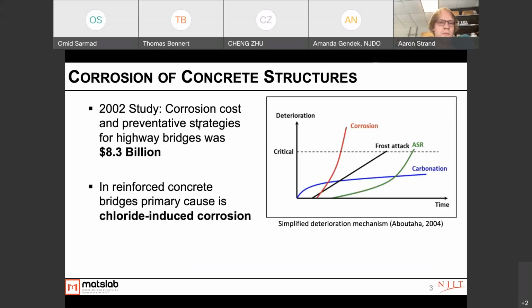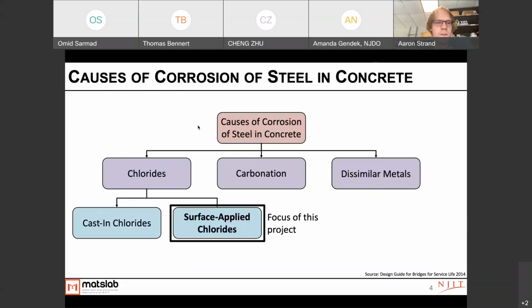So why are we concerned about corrosion? In a 2002 study, it is an $8.3 billion problem for just highway bridges. In reinforced concrete bridges, the primary cause of deterioration that we see is chloride-induced corrosion, compared to other types of deterioration such as frost attack, ASR, and carbonation. The three major causes of corrosion of steel in concrete are chloride, carbonation, and dissimilar metals embedded inside the structure. With chlorides, we sometimes see cast-in chlorides, but we'll most likely see surface applied chlorides. That's the focus of this project.